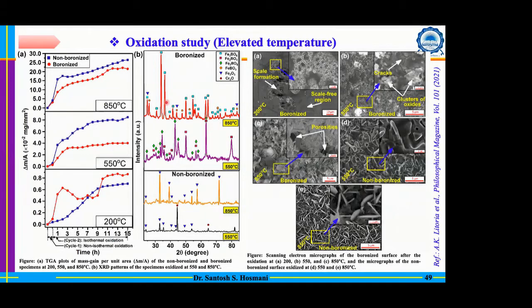We studied this composition using Raman spectroscopy, and we realized that during the oxidation there is a formation of various oxides. Some of the boron oxides have a lower melting point. Because of the lower melting point, these oxides will spread and cover the entire surface. That iron boron oxide, which is shown in the XRD pattern, is uniformly covering the surface, and it is basically helping to avoid further oxidation at elevated temperature. That is the mechanism helping us.